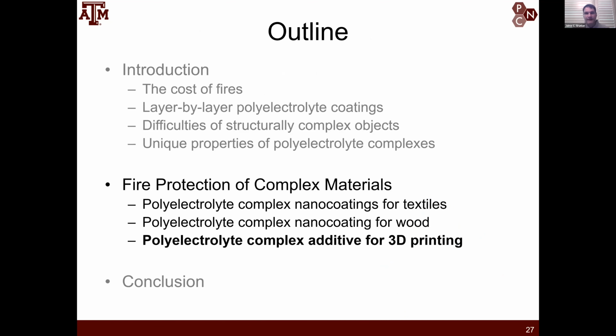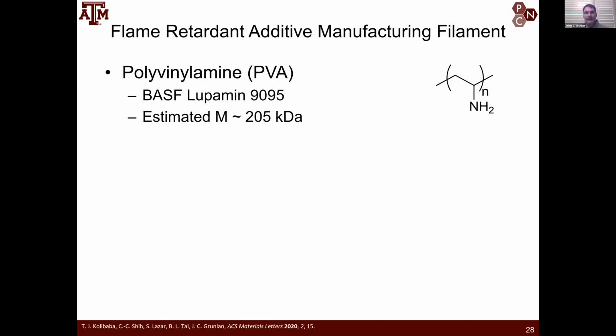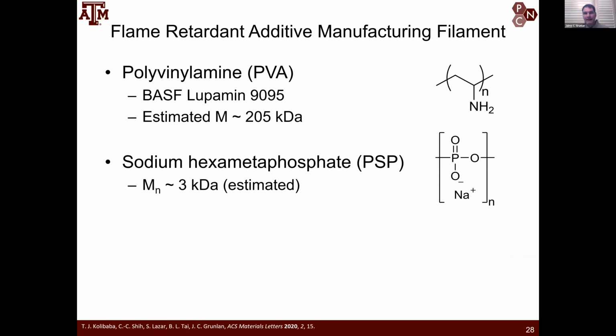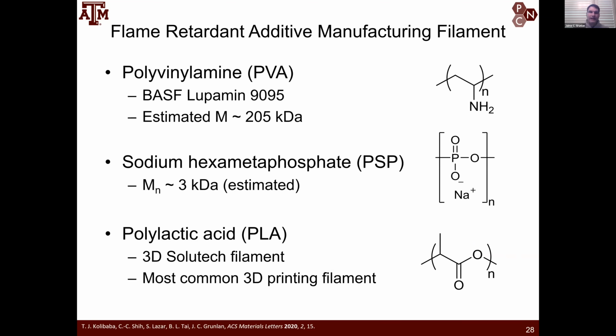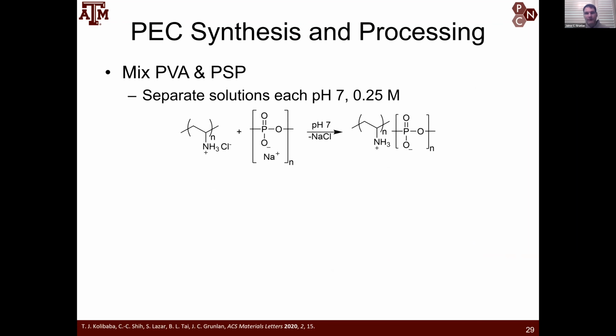Finally, I wanted to mention the fused filament 3D printing. In this case, we took polyvinyl amine and made a complex with sodium hexametaphosphate, the PSP that we've seen before. And then we blended this complex with polylactic acid. PLA is a very common 3D printing filament. And when we made this combination filament that had the polyelectrolyte complex plus the polylactic acid,